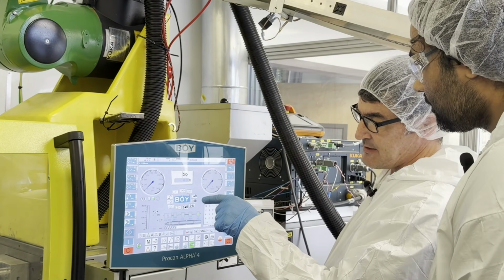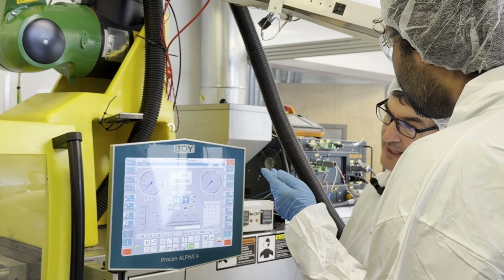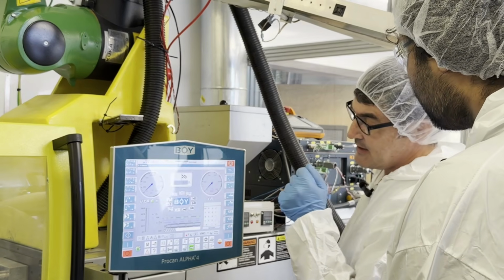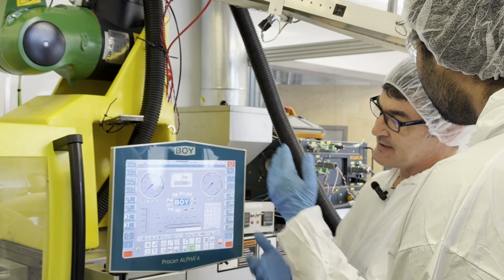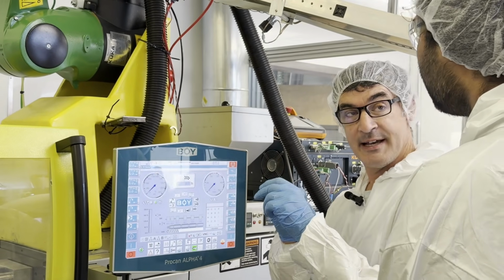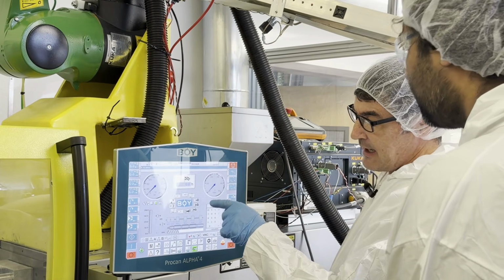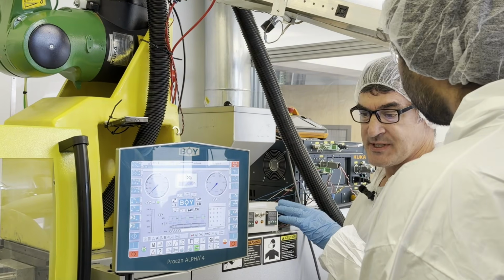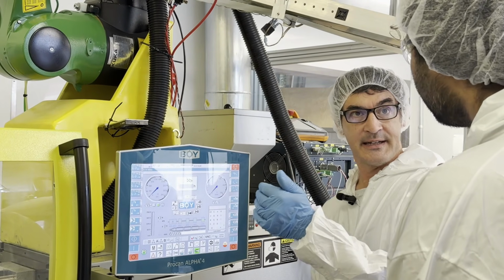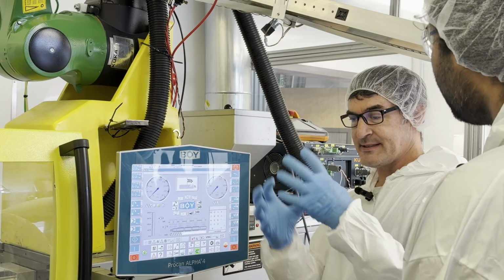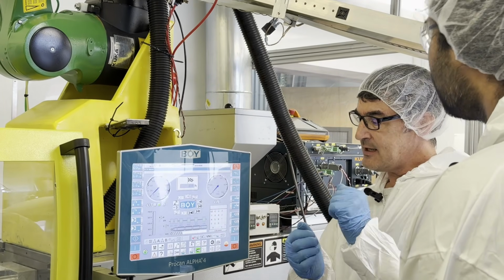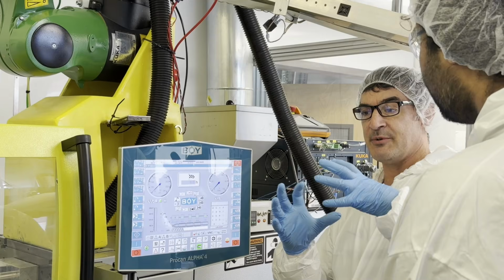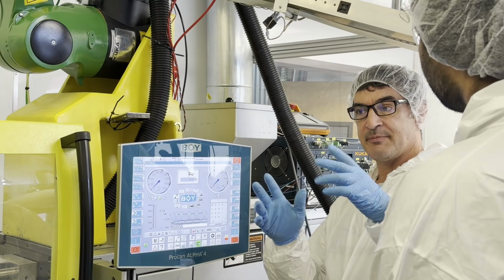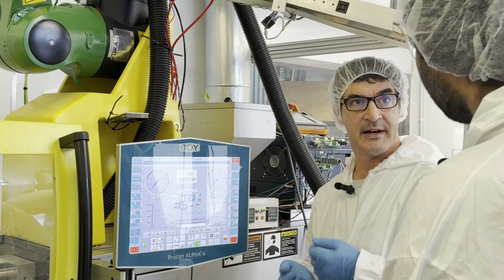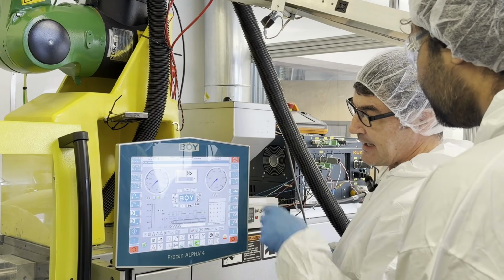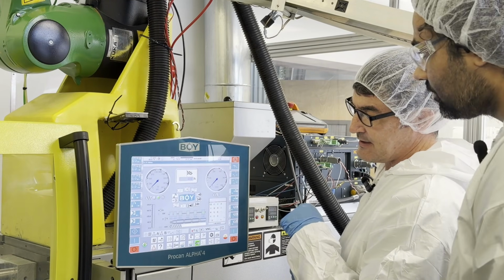The next step after that is the molding machine will switch to a packing phase at a prescribed distance of the amount of plastic or the shot size that's entered into the mold. And in the packing phase, the machine switches to a high pressure and a low velocity or a low flow, because it's just filling out the last 5% of your part and pressing against the mold cavity walls to pick up all the detail of the mold itself onto your plastic part. And that happens for a few seconds.